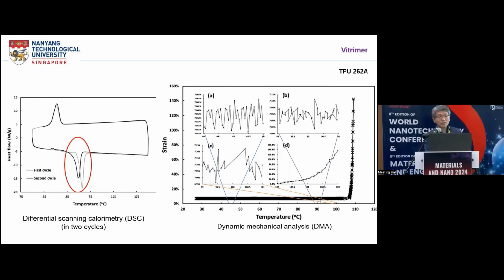And even if you heat up to 100 degrees, the material is still able to maintain the shape. The strain is not so periodical in response to periodical load, but it still maintains the shape mostly, unless you heat up to over here. Then you will see the material lost the shape, so it becomes thermoplastic, easy to flow. So this is a particular feature of vitrimer. We can cross-link the vitrimer. Of course, it's not particularly designed for the application we're going to use. Later, I'm going to mention some other material which we have developed.